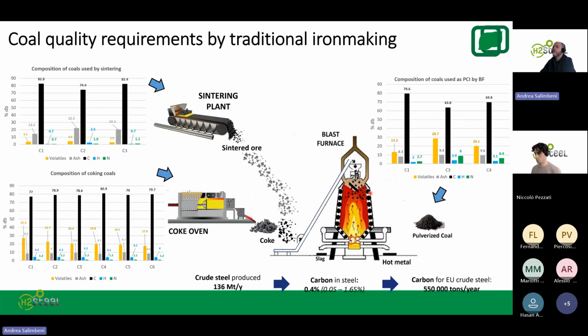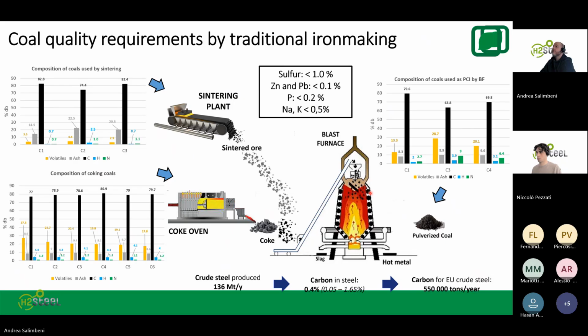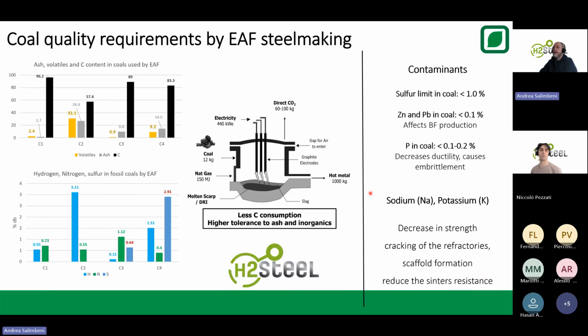So what is the target? We need to produce a coal with reliable quality to replace fossil one. So we have to produce something of low volatile content, high carbon content, and in particular, we need to avoid contaminants that are critical for the steel quality, like phosphorus, potassium, sodium, and sulfur. That is our target. Do we want to decarbonize the steel sector? If we want to do that, we need to introduce new reducing agents like hydrogen and bio-based coal. And that is what H2STEEL is doing. Regarding the electric arc furnaces, the limits are the same. If we want high quality steel, we need to produce a coal alternative with low volatile, high carbon, and low contaminants, low sulfur, low phosphorus, low zinc, low lead.